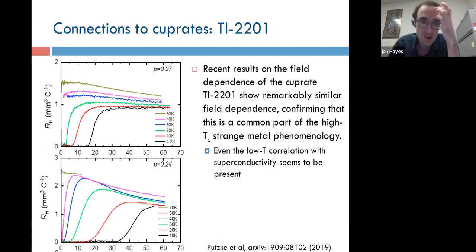So first, I want to acknowledge that there's some recent nice work actually coming from Nigel's group on the field dependence of RH in thallium cuprates. And there are some qualitative consistencies here, where the Hall coefficient decreases with field, and that weakens as you go to lower temperatures on the overdoped side. I'll leave it to you to read that paper and determine how similar you think they are. But I think it's a very interesting point of comparison and suggests that something about this may be universal to all these high TC materials.